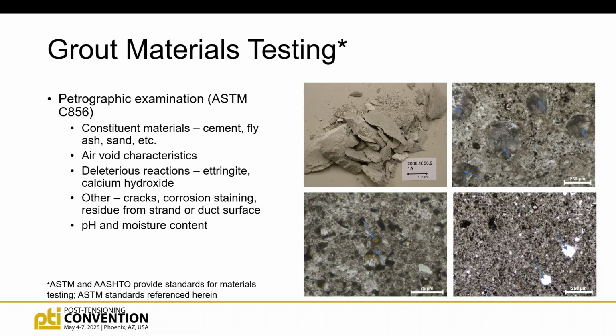And so on the right here, these are just very close-up air voids. These are ettringite, ettringite would have rings around them. No, I'm sorry, this is the ettringite, and then this is the fly ash particles that have rings around them. So, it is useful in that sense.